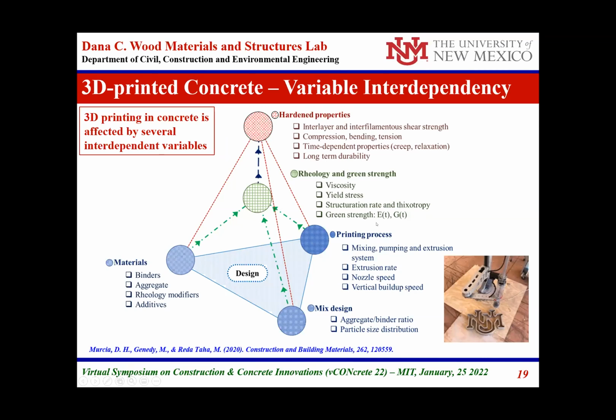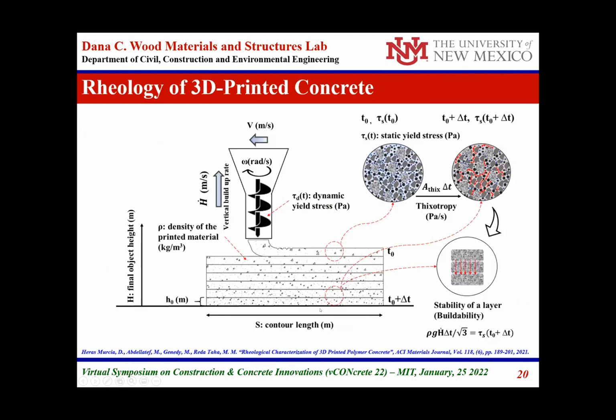All of those factors, along with the rheology, affect the hardened final properties of the concrete. In this model, we show that as you are placing the concrete and the concrete is sheared here in the printer, this shearing ability is a function of the dynamic yield stress of the concrete.